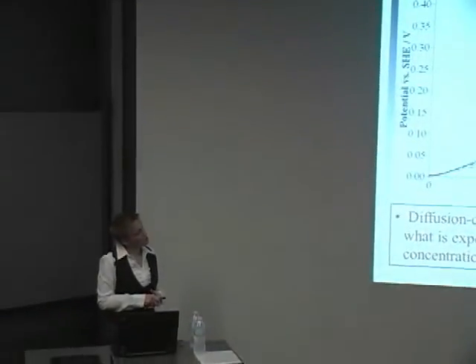We believe that this self-discharge that we still see even when we bubble the electrolyte with nitrogen is oxygen reduction of the oxygen that's deep in the pores that we are having trouble removing. So for a commercial system, you're going to still see this self-discharge, and we have not yet found a way around that.